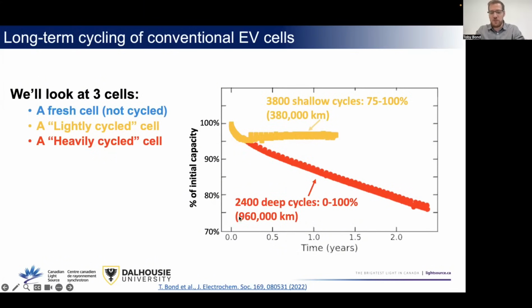And we cycled it for 2,400 cycles, which, if you have a 400 kilometer range EV, is the equivalent of driving just under 1 million kilometers. And we cycled it from 0 to 100%. So this is very abusive conditions. You would never cycle all the way down to 0 and charge all the way back to 100. But if you did, this is the kind of difference in capacity fade that you would get. So it makes a big difference off the top. We don't need a fancy synchrotron to see any of this. You can tell it just from this data.